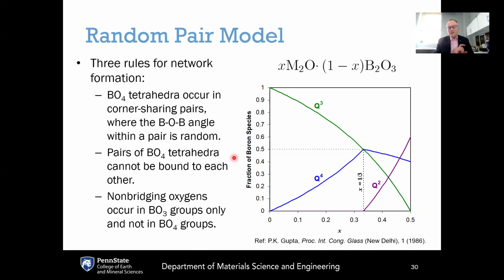And mathematically, the random pair model gives us equations that describe how many of the borons are in Q3 units, meaning these are trigonal borons with three bridging oxygens, versus Q4 units, which are the tetrahedral boron groups, versus Q2 units, which are the trigonal boron units that have one non-bridging oxygen and therefore only two bridging oxygens, reflected in the superscript here too. And what we see with the random pair model is that all the borons start off in Q3 units here if you have zero modifiers.